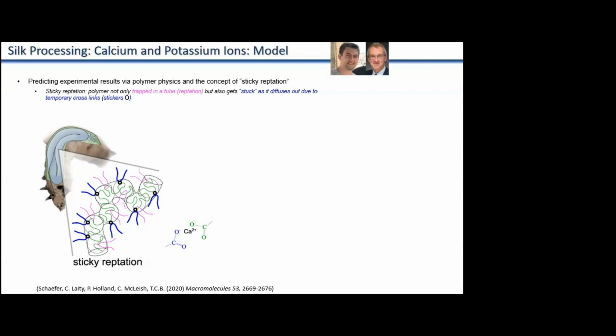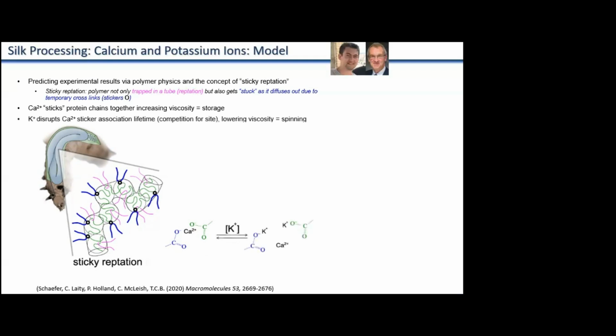But when the animal wants to start spinning it, it can start popping in some potassium, a monovalent ion, which eats up all the stickers, stops the divalent ions, shrouds the silk molecules, and prevents them from interacting with each other, loosening it all up, reducing the viscosity and allowing the silk to be spun. And that is a concept known as sticky reptation, basically an additional molecular interaction that affects the polymer physics and the flow properties itself.